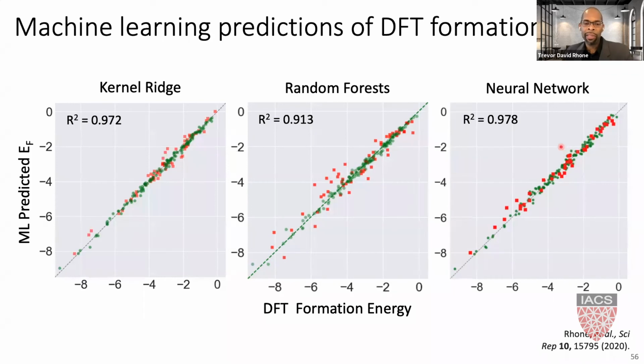Typically, this doesn't happen for materials data because neural networks typically require a lot of data. They're data hungry because there are many coefficients that need to be tuned. And our data set comprises about 200 structures. So this is surprising, but for the formation energy result, it seems to work out pretty well.